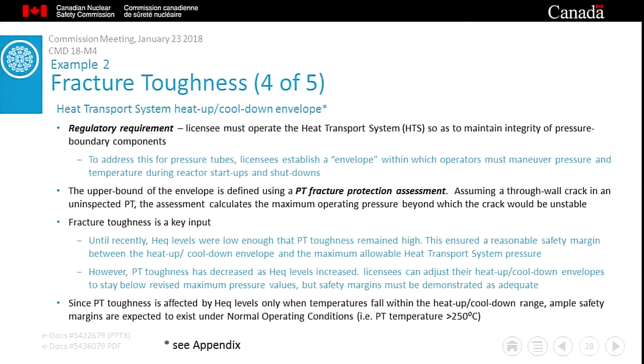You have a crack in a pressure tube and you have not identified it. So to develop the heat up cool down envelope, the licensees start by assuming that there is a tube out there that has that crack. A key input to this assessment is fracture toughness. As I mentioned earlier, the temperature range over which heat up and cool down occurs, known as the transition regime, is tricky because the toughness varies both with temperature and with hydrogen equivalent level.